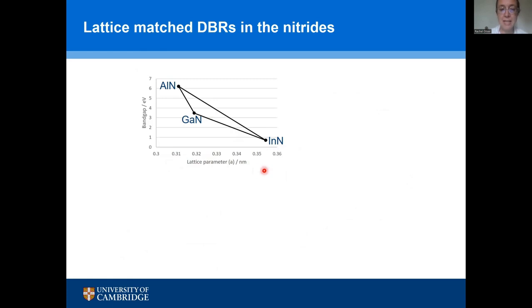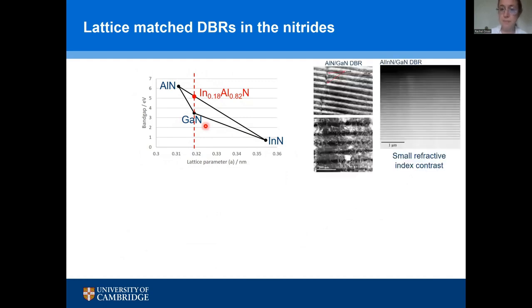So here I've got the lattice parameter against band gap, and we've got gallium nitride and aluminium nitride, which do have different lattice constants. But if we look at the alloy between aluminium nitride and indium nitride along this top line here, then there is a composition, indium aluminium nitride with 18% indium, which has the same lattice parameter, the same atomic spacing as gallium nitride. So from that, we should be able to make beautiful lattice matched DBRs. And indeed you can, actually.